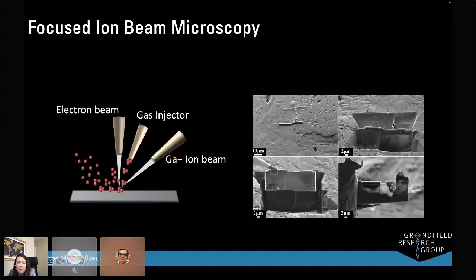We can then use a small micro manipulator to pluck this section out. And then we use the ion beam again to thin this section until it's less than 100 nanometers and we can see through it with a transmission electron microscope.